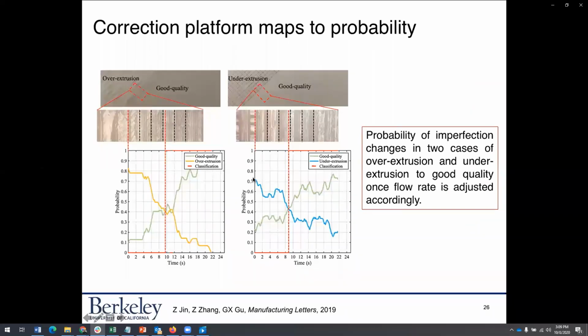And this is seen also in the probability. Our algorithm is telling us the probability of something being under extruded is quite high, and the probability of something being good quality is quite low. From there, we want to adjust the printing parameters. In this case, we're adjusting flow rate, because flow rate really dictates whether a sample is over extruded or under extruded. And in this case, we're going to increase flow rate. Then you can see the sample starts to increase in probability of becoming good quality, and decrease in the probability that it is under extruded.